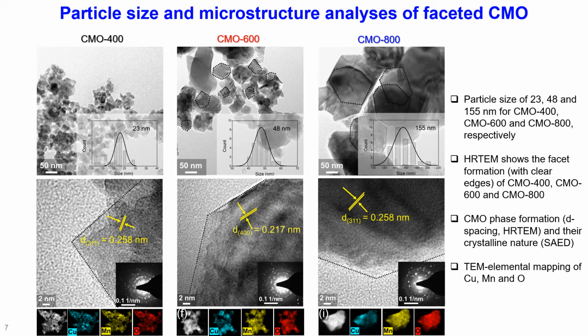Here we also confirmed the formation of cubic CMO from the d-spacing value obtained from HR-TEM, which coincides with the d-spacing value obtained from XRD. Then the good crystalline nature of all three samples has been confirmed from the SAED pattern. Finally, the uniform elemental distribution of Cu, Mn and oxygen in CMO nanopolyhedra has been confirmed from the TEM elemental mapping.